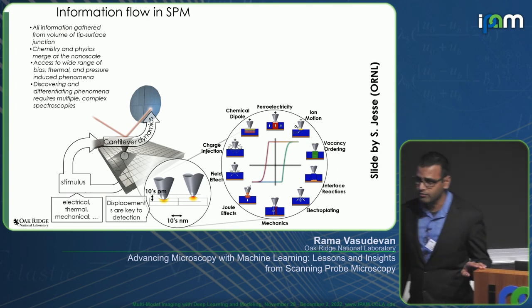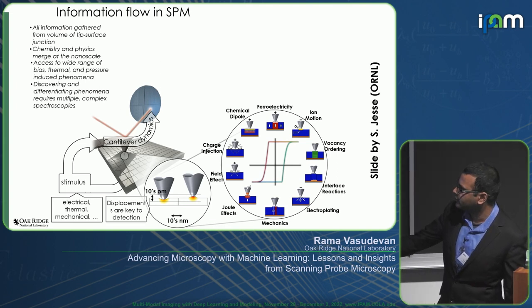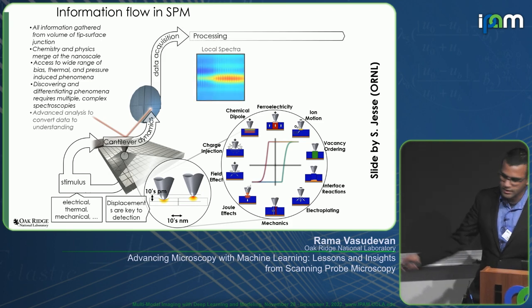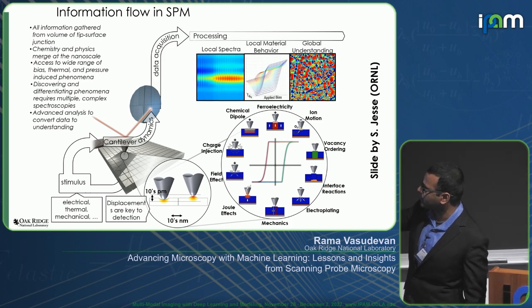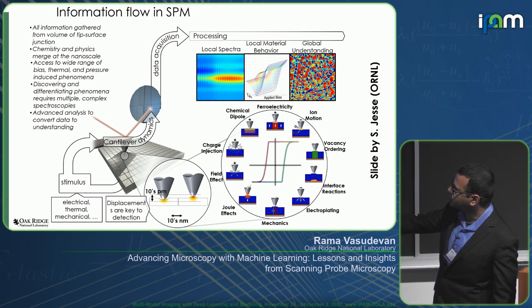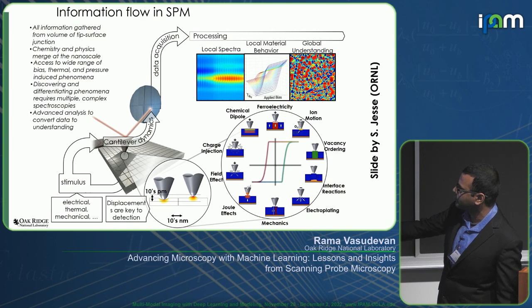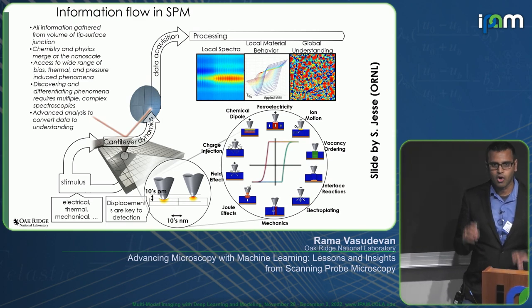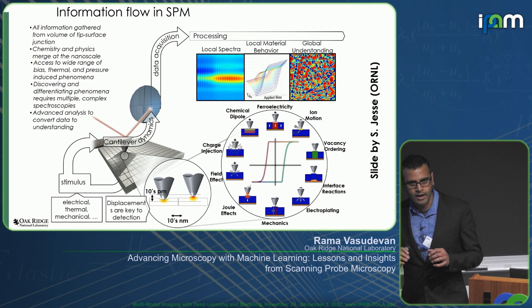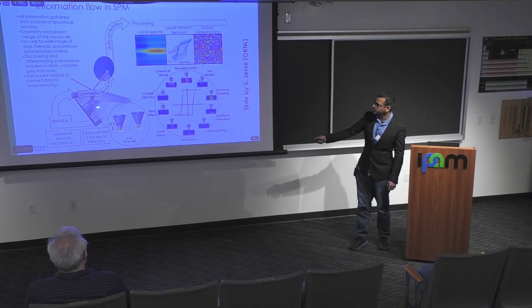But the trouble with a lot of AFM is that typically our signal is convoluted with the cantilever dynamics that you need to measure and understand. You need to perform some processing on the signal so that you can hopefully get an understanding of local materials behavior. So let's say we apply some stimulus to this probe. We get some spectra at that particular location, and then we build up a map of the spectra across the sample. Hopefully, this leads us to a better understanding of our material system. So the goal in any scanning probe microscope is really to understand how the local microstructure, which we measure, correlates to the functional properties, which we also measure through the same microscope. And that's really the goal of any type of microscopy.